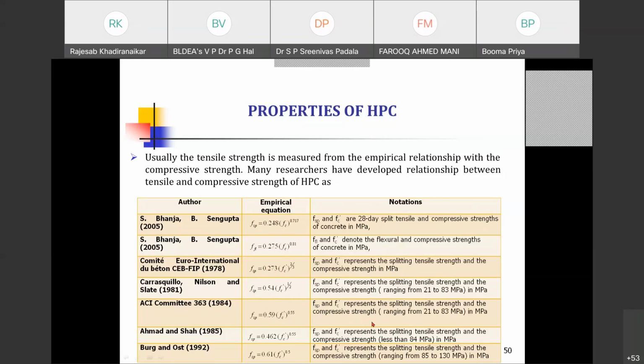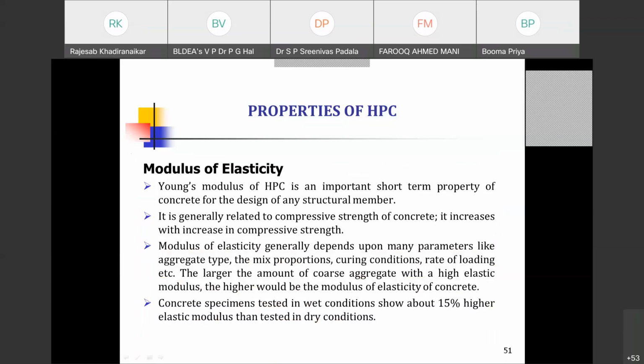And then the ACI committee proposes 0.59 f_c' raised to 0.5, and it is applicable to 21 to 83 MPa, they say. And Ahmad and Shah in 85 proposed 0.462, and up to 84 MPa you can apply this. Like this, many expressions are there, and whichever suits your requirements, accordingly you can use.